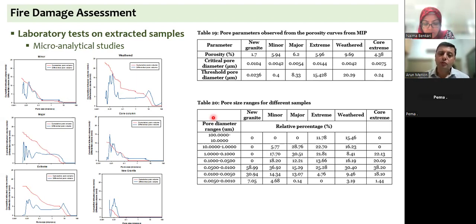Small pores were beginning to join larger pores, and there was a change in the micro pore structure in the outer portions of the stone, not so much in the inner portions of the stone. So we were able to see that the columns that were possibly affected in a minor way or in a moderate way still had good core strength, which we can depend on. So that was some sort of an insight we were able to get. And in certain cases, the pore size was also changing because of expansion of some materials.